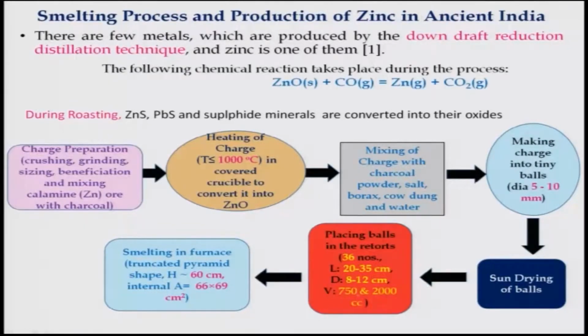And then of course, it will be placed, and then it will be put into the smelting furnace, which I will show in detail, which is of a truncated pyramid shape, and then it will be heated to a little higher temperature. As a result, the zinc oxide will react with the CO, which is produced by this charcoal, and then zinc will be produced, and also carbon dioxide. The zinc will be in the vapor state, and then you will have to condense it to get the zinc metal.